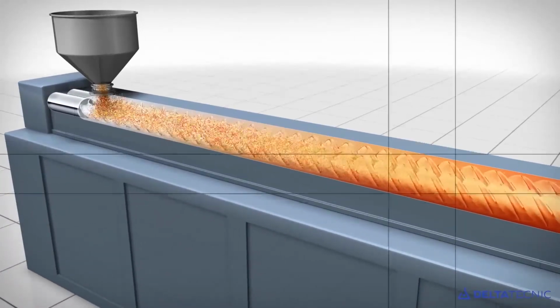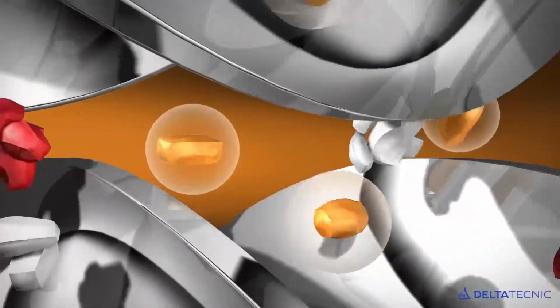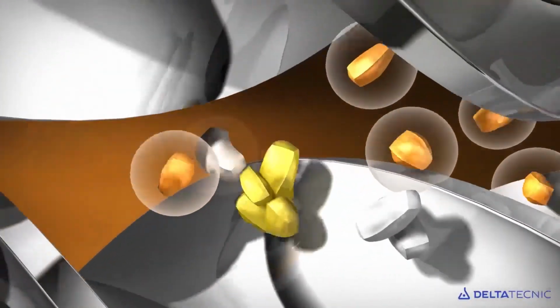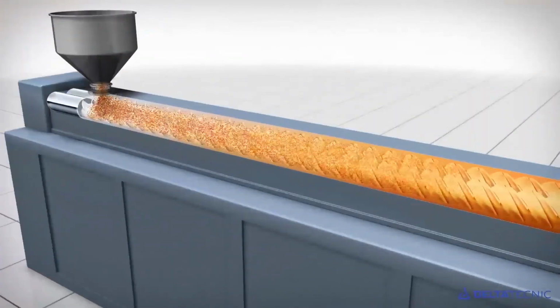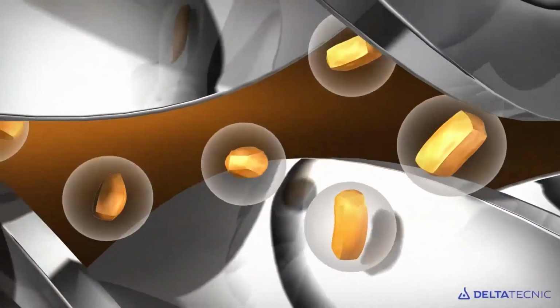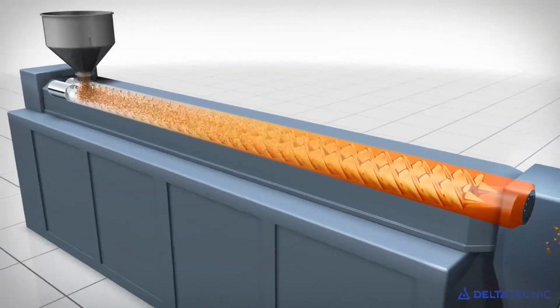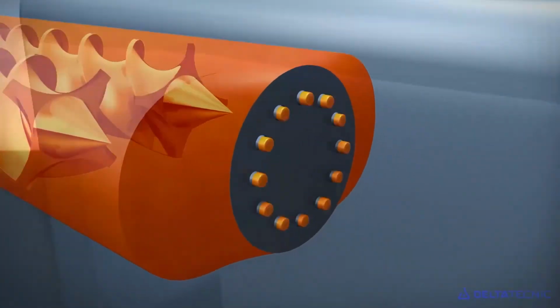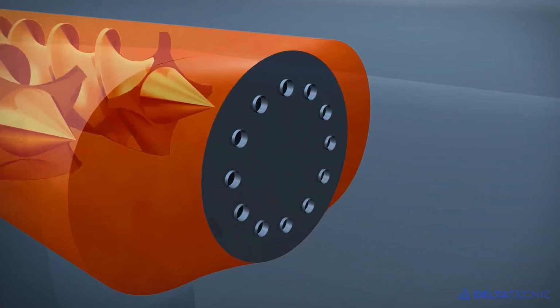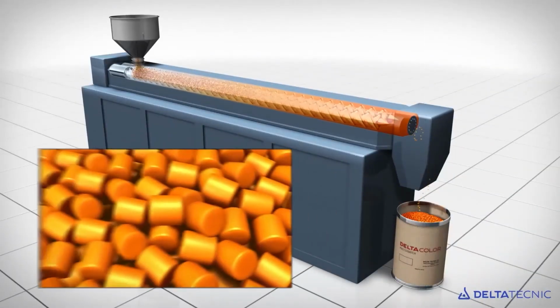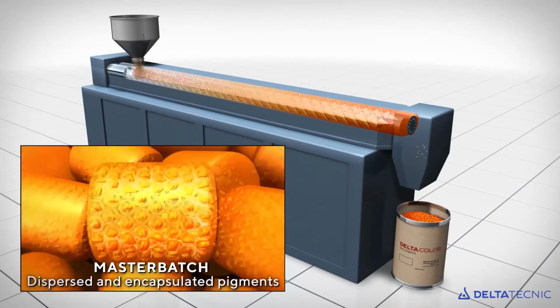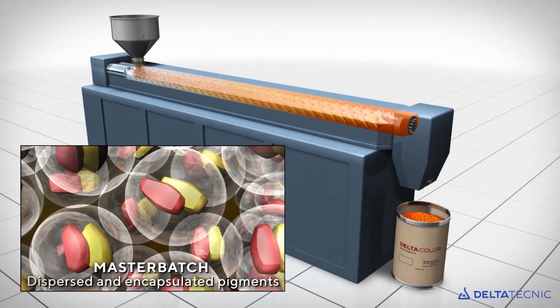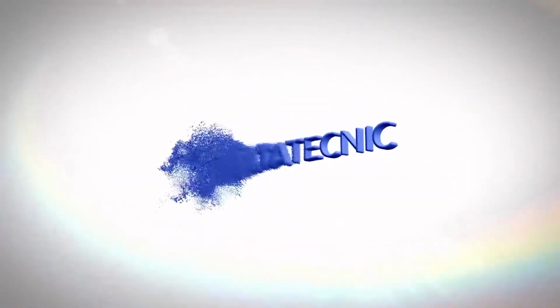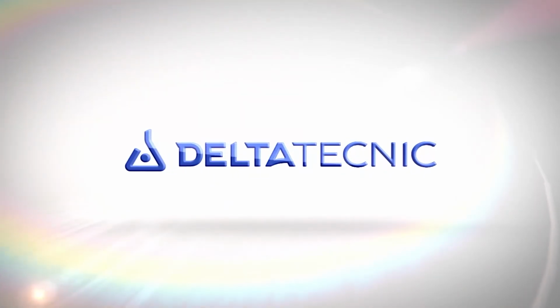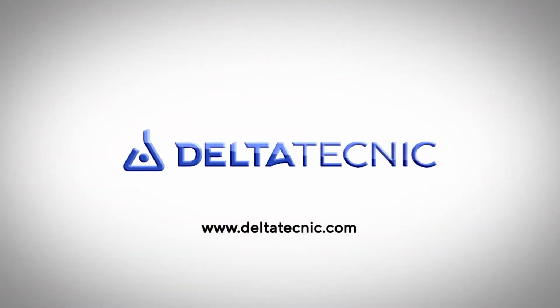And once they are all dispersed, then at the header of our twin screw extruder, we cut them and produce the pellets. And you can see at a microscopical level all those single crystal units of pure pigment dispersed and surrounded, at microscopical level on the pellet, as you can see here inside the pellet. So this is what we call dispersion, right? So let's go back to the presentation. Here we go.